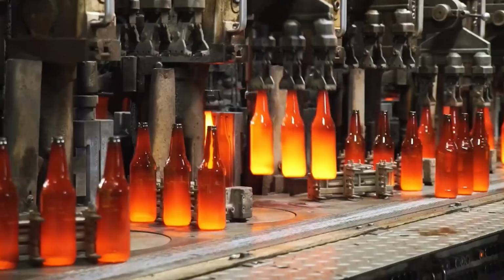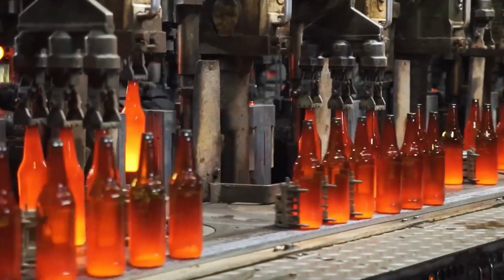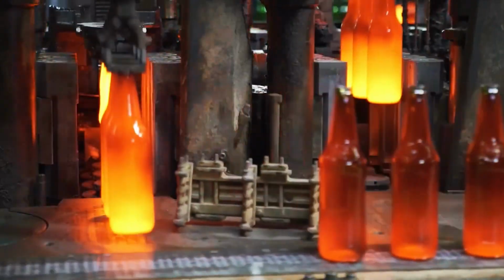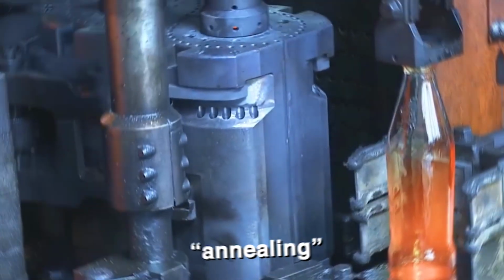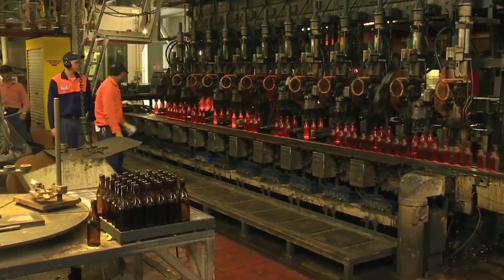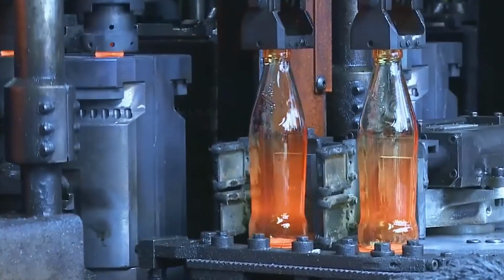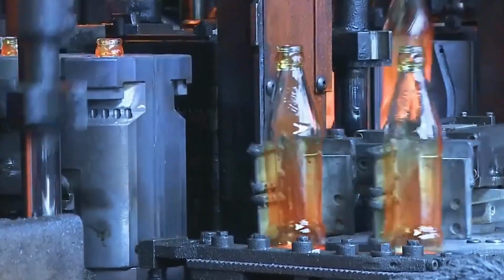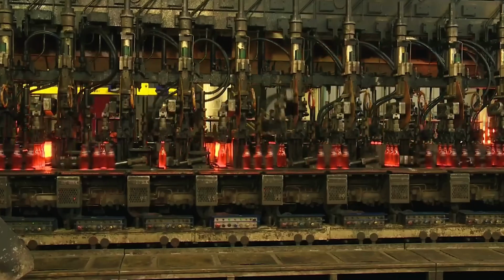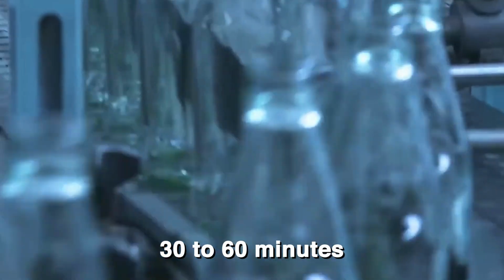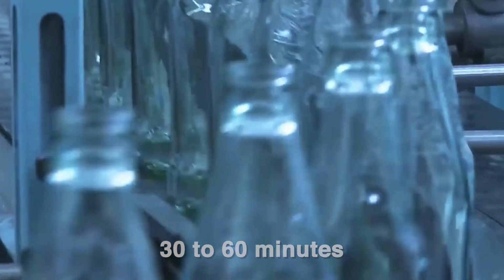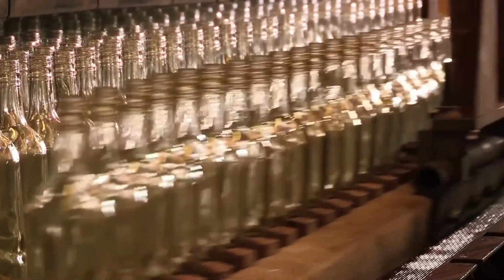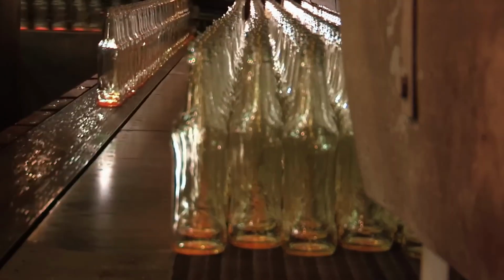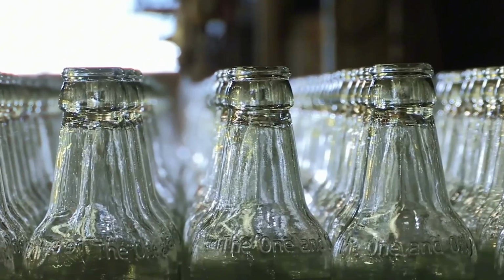As the freshly formed bottles travel along conveyors, they slowly cool through a process called annealing. This prevents internal stress and cracking by gradually lowering the temperature inside an annealing layer, a long tunnel-like oven. The journey takes 30 to 60 minutes, during which each bottle's temperature drops from around 600 degrees Celsius to room level. The rhythmic clinking of cooling glass fills the air, a sound that defines the heartbeat of the factory.